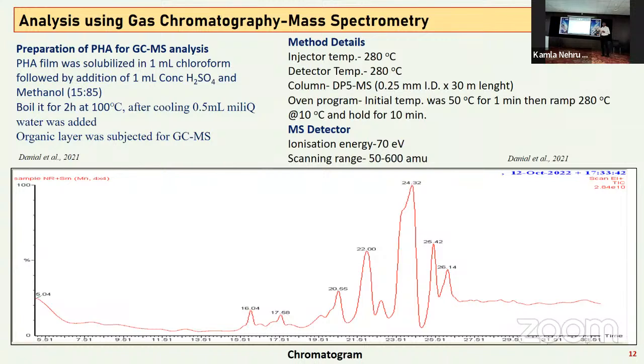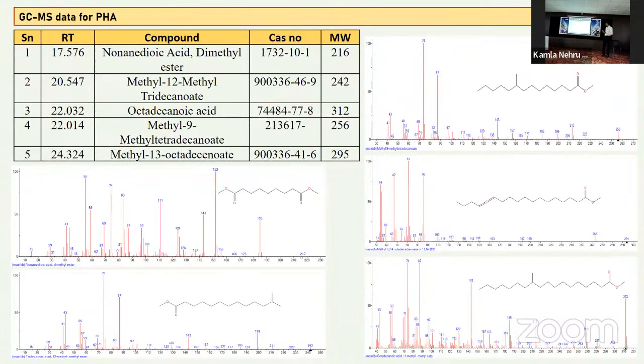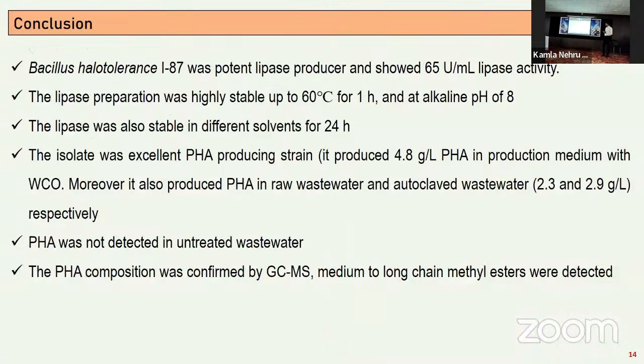Okay, so this was characterized first of all by GCMS because we wanted to know is it polyhydroxybutyrate or what monomers are present in it. So by GCMS we got several things indicating that it consists of many different fatty acids, which are shown in the next slide. If you see the composition, it varies from C9 to C13, then C18 and C14. So you can see C9 to C18, different chain lengths inside. So it was a mixture of different kinds of beta hydroxy acids. So you can say it's a medium chain length polyhydroxyalkanoic acid, not corresponding to really butyric acid, which is more common. So this can be a good substitute for a flexible kind of plastic like polyethylene.